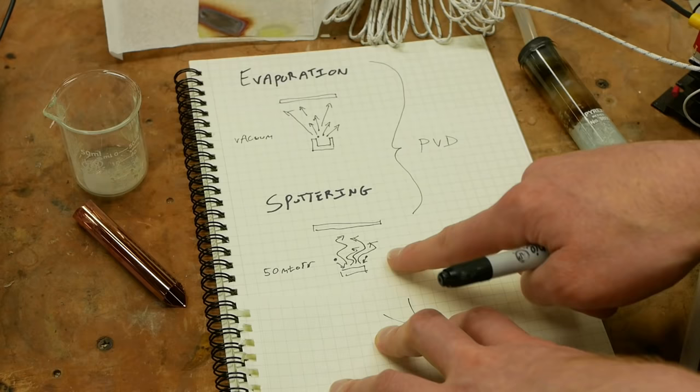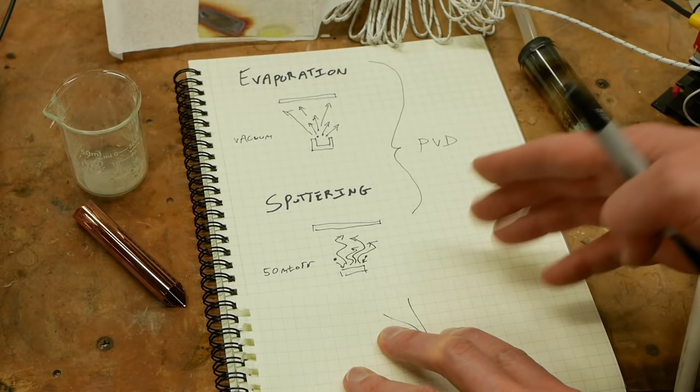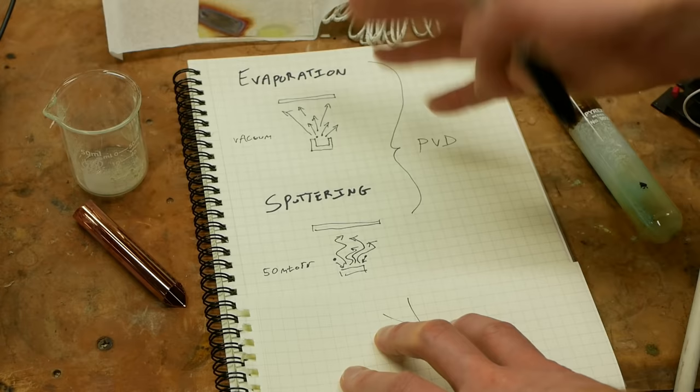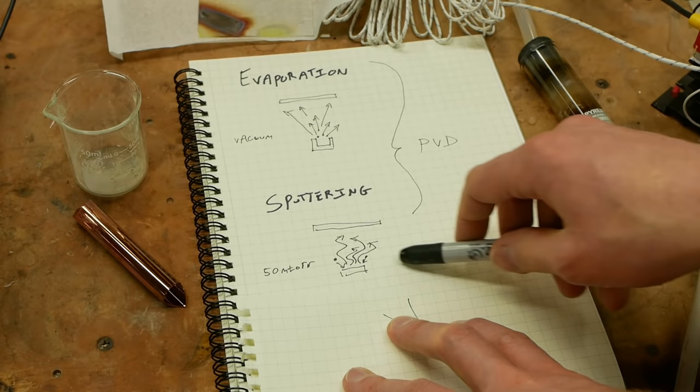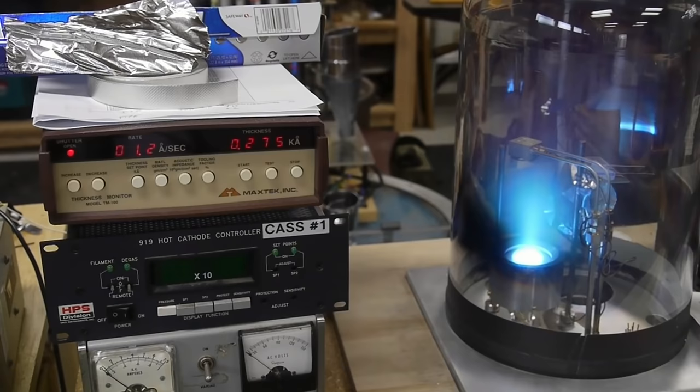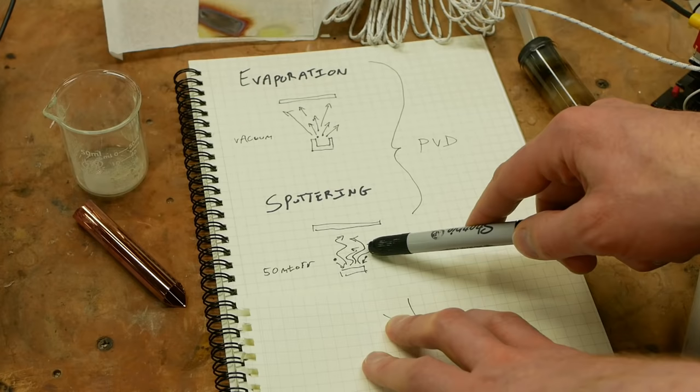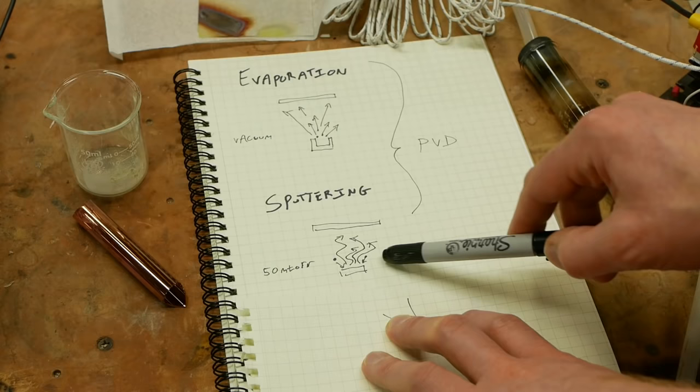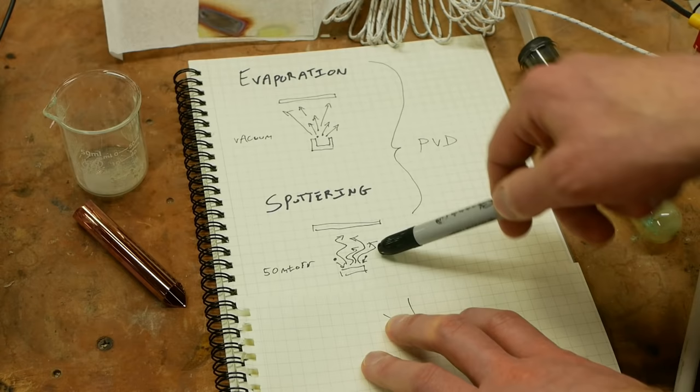You can also kick things up a notch. For example, instead of putting argon in or in addition to argon, we could add something like oxygen. So if we were sputtering titanium and we had argon and oxygen up here, when a titanium atom gets ripped off the surface, it can react with the oxygen and become titanium dioxide. Then when it hits the surface, we've now formed a layer of titanium dioxide. And that's much easier than trying to sputter titanium dioxide itself. But the point is that you can have a chemical reaction in this cloud of plasma and it opens up possibilities to make a whole bunch of different compounds here by adding a process gas.